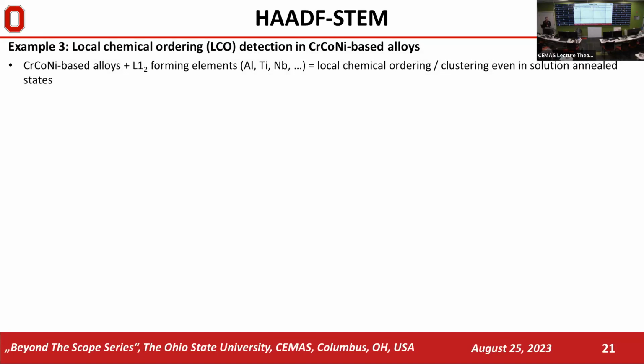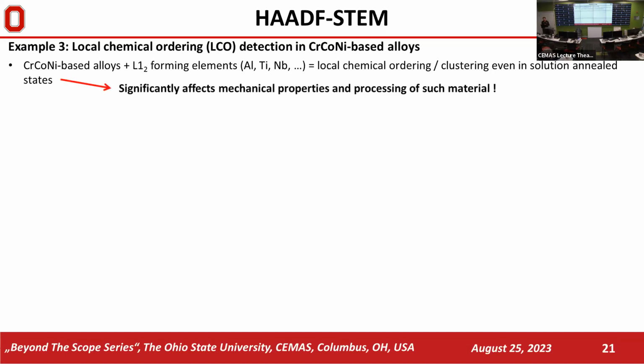Another example: I got a lot of questions after the paper was published that in the GRX alloy we studied, we were trying to figure out if there's local chemical ordering, and we didn't find anything, but there were questions like, are you sure about that? So it's known that if you have chrome-cobalt-nickel based alloys and you add elements such as aluminum, titanium, niobium, which are L1_2 forming elements, local chemical ordering or clustering can happen even in the solution annealed state. In chrome-cobalt-nickel based alloys, there are also other types of chemical ordering, but this specific ordering associated with aluminum, titanium, niobium, it's possible to very simply detect using high-angle STEM. This is important because this significantly affects mechanical properties and processing of such material.